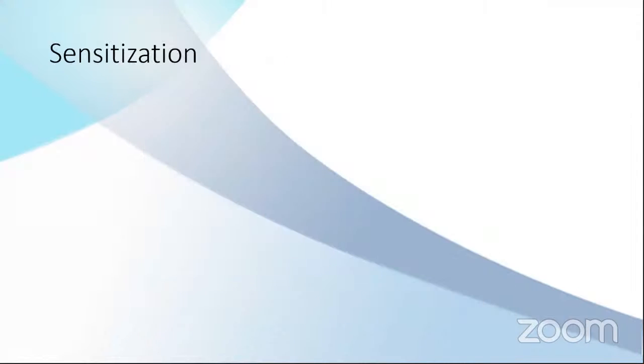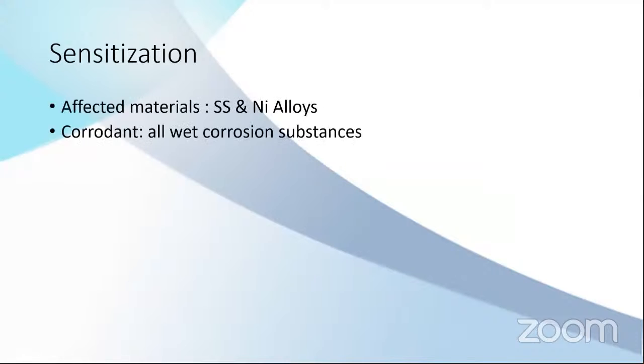So okay, previously it was PW corrosion for carbon steel. Now it's a sensitization problem. This is for stainless steel and nickel-based alloys. So when the stainless steel or nickel-based alloy is sensitized, any corrosion can start on the material. So any corrosion, seawater or acid or anything, because it's already losing its corrosion resistance.